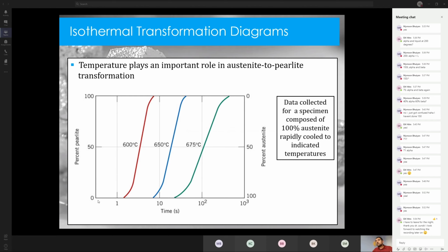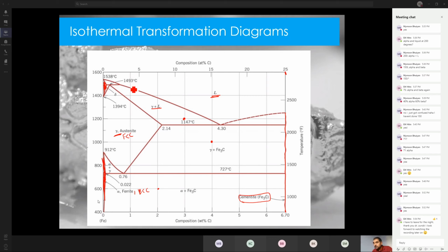The nice thing here is we can look at an example where austenite, let's say, have a steel of composition 0.2, which is heated up here. That's what typically happens during the hot rolling of the steel when they're forming it at high temperature. So it's austenite or gamma, and now I'm cooling it down. And once I get to this temperature here, it should transform to alpha plus Fe3C.